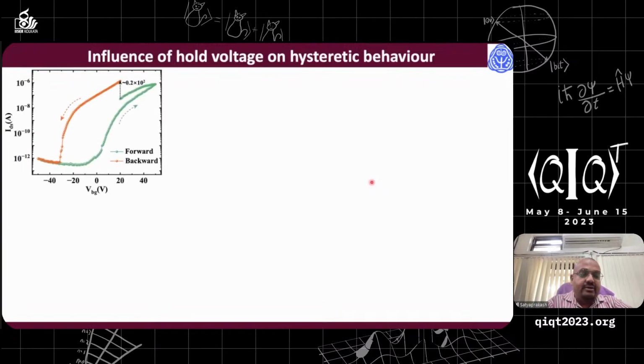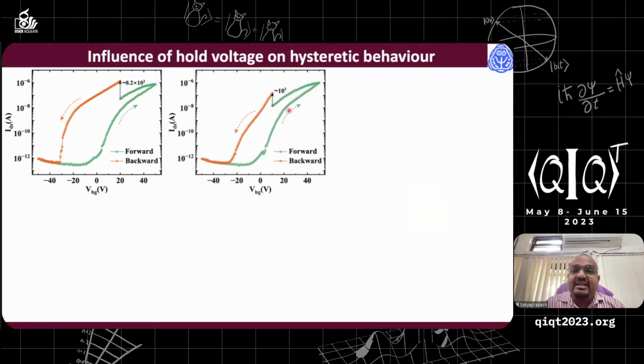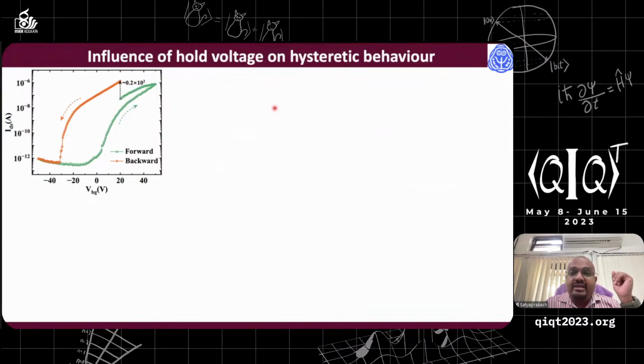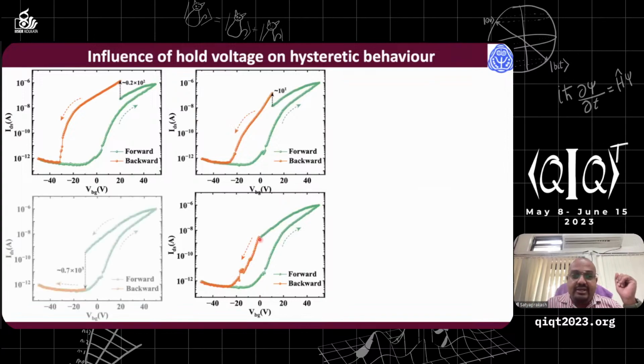Now, another interesting result that I would like to show you: you go in the forward direction, then wait at a particular voltage, particularly in the positive cycle. You just hold the experiment there and wait, say we waited for 6 hours for this particular experiment. Then we do the experiment. After 6 hours, we see the backward current increase, but we do not know how the current changes in real time during these 6 hours. That I will show you. Here the stay is at 20 volt, here around 10 volt or so, here at 0 volt, and here at negative volt.